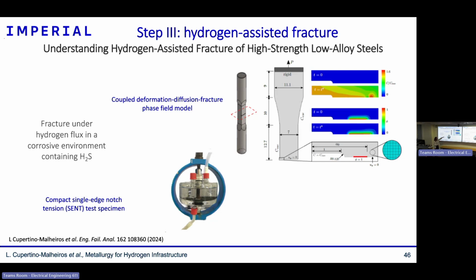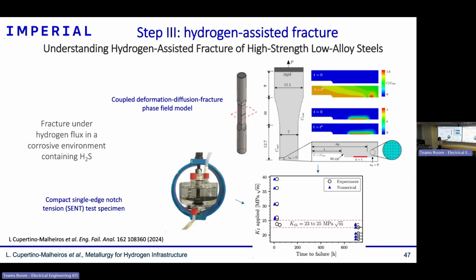So for the numerical test, again, the same geometry, which here can be modeled by half of this plate in 2D. And here it's applied a coupled deformation, diffusion, fracture model. So we capture all the physics involved, and now we do the same test, but a numerical test. And those are the results of this test.